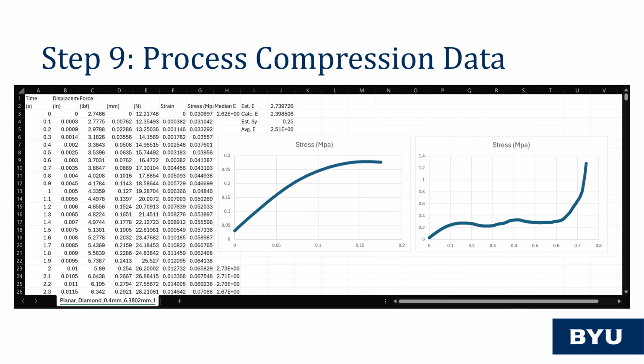After exporting the data, each CSV file was then processed to convert the inches displaced and the pounds force applied to millimeters and newtons. This data was then used to calculate the stress in megapascals and the strain of the model over time. The graph on the right shows the full stress strain curve of the diamond lattice. The graph increases linearly as the lattice structure behaves like a pseudomaterial until the yield strength of the individual lattice joints are met, after which the structure plastically deforms and creates a new pseudomaterial. This process repeats until the lattice members are in direct contact with each other and the lattice is essentially eliminated, leaving the sample to behave like the bulk material.